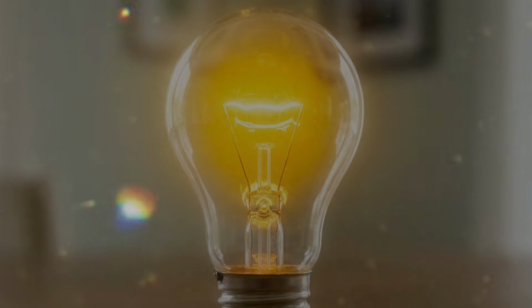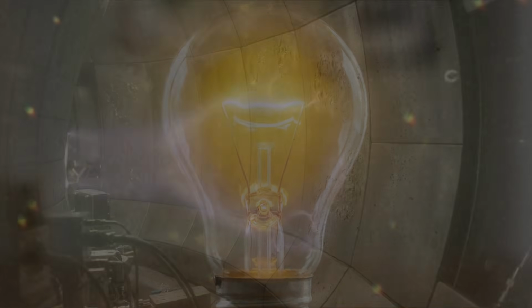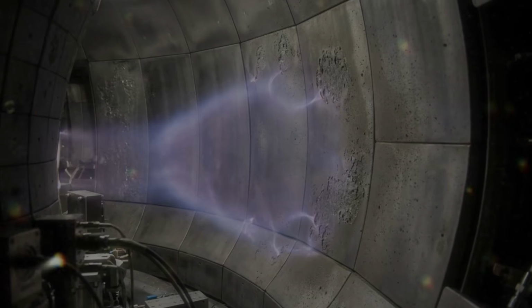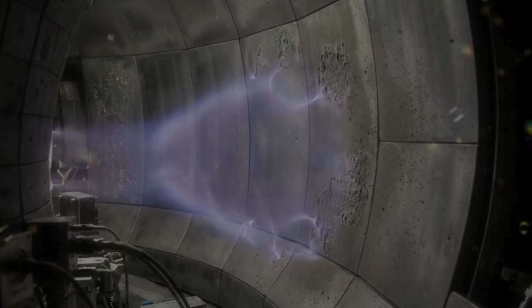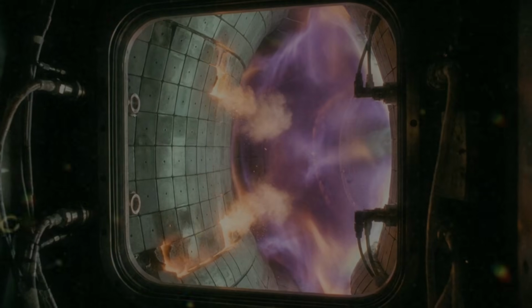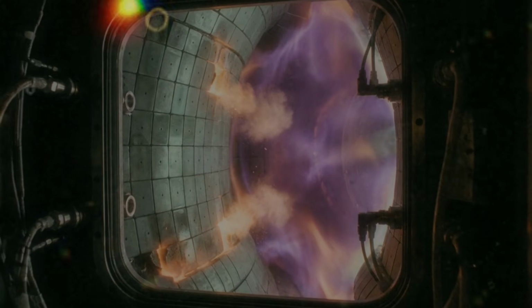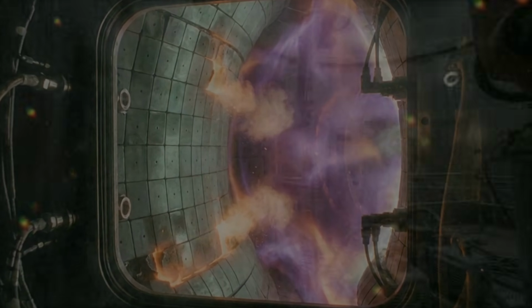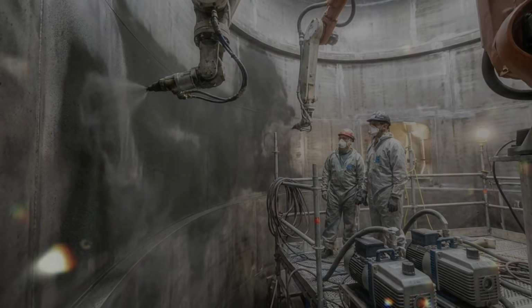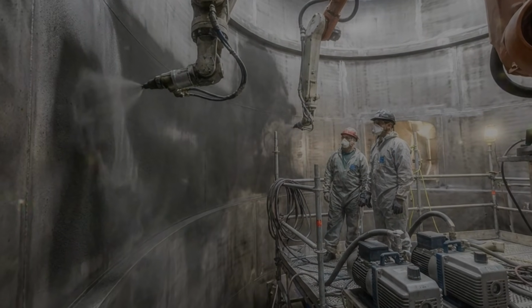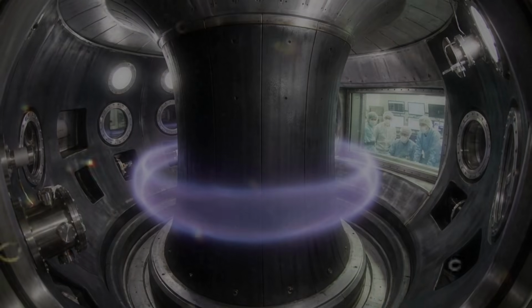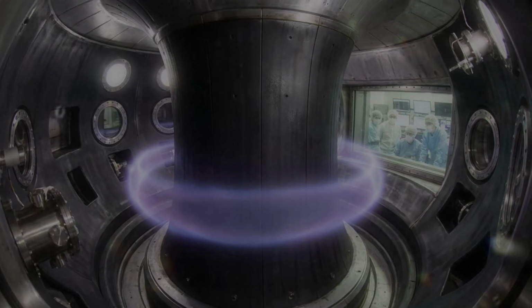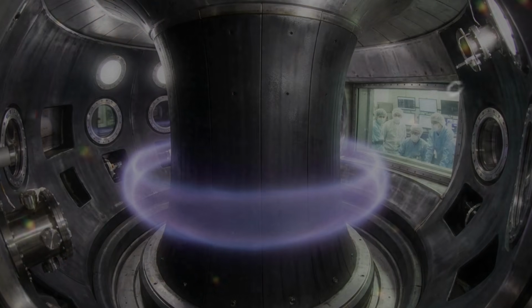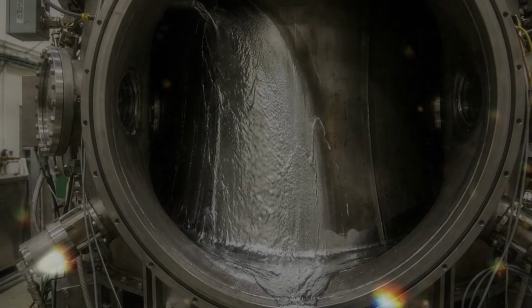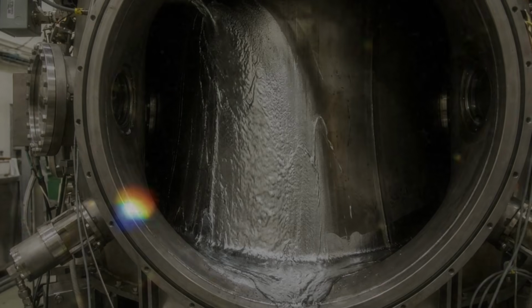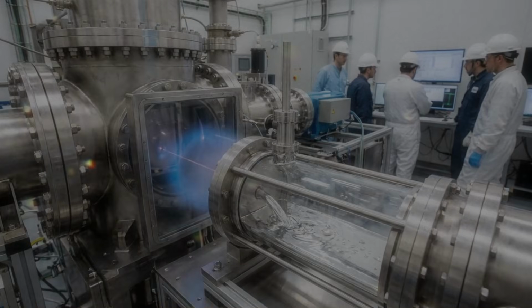There is another subtle issue. Neutron damage can reduce thermal conductivity. Thermal conductivity is the ability of a material to carry heat. If the wall material becomes worse at conducting heat, then its surface may run hotter under the same conditions. Hotter surfaces may crack more easily, erode faster, or retain more fuel. So neutron damage can make heat damage worse. Heat damage can roughen surfaces and change plasma interactions. Plasma interactions can increase erosion and fuel retention. Everything connects, which is very satisfying in a textbook and very annoying in a reactor.